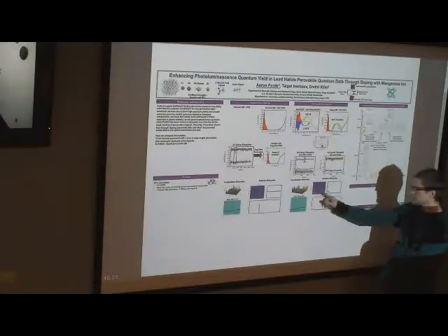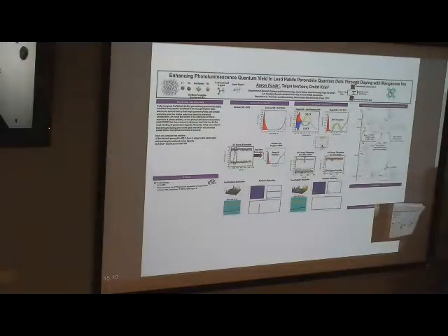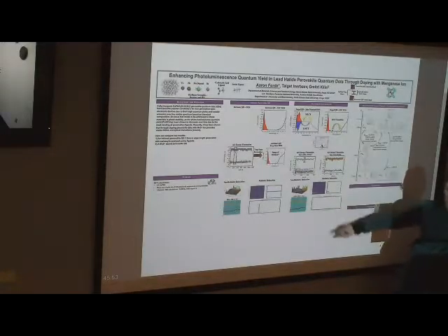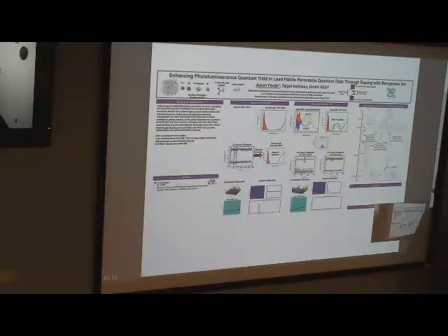But once it gets to the gap, there's a very faint excitation corresponding to about 700 nanometers, which is a little bit lower in energy than what's experimentally reported for this transition dopant, but about in the right spot, but it's very low over time. And that's the opposite of what we expected to begin with. We expected this peak to be higher over time, just due to the emission being unaffected by the trap states.